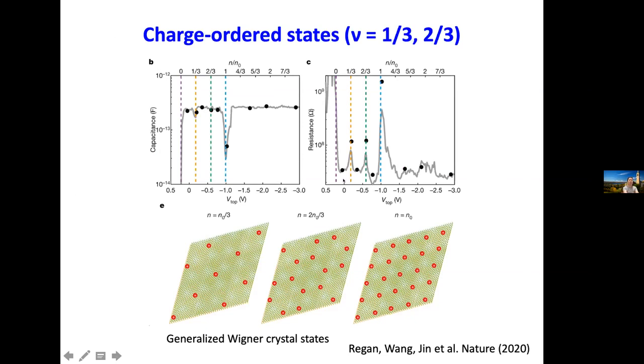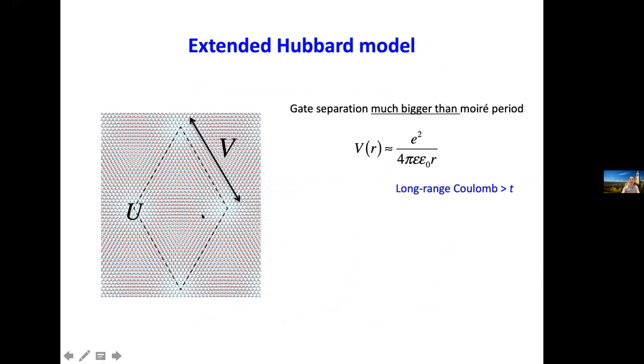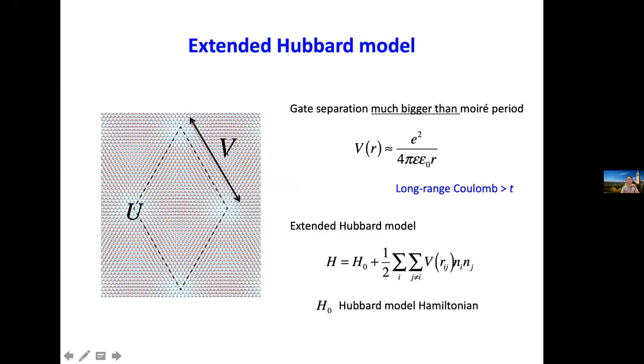The emergence of these generalized Wigner crystal states suggests that even the intersite, long-range Coulomb interaction is important, because the particles are trying not just to avoid occupying the same site, but also to avoid the neighbors. This tells us that the simple Hubbard model needs to be modified to an extended Hubbard model, because the gate separation is much bigger than the Moire period. So the long-range Coulomb energy can also be significant compared to the intersite hopping. This is the extended Hubbard model.